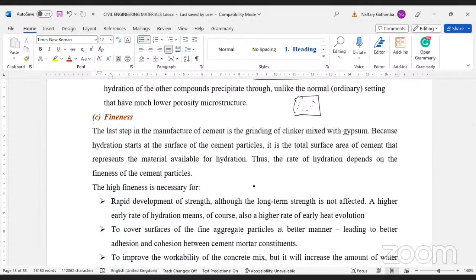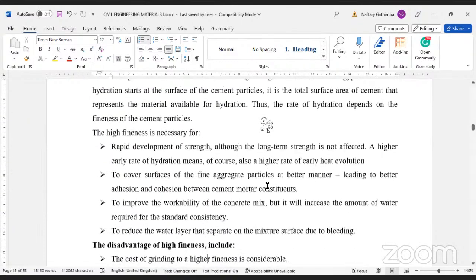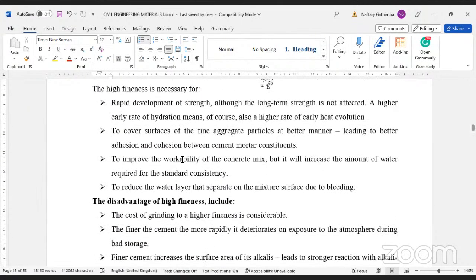So the last step in the manufacture of cement, we saw, is grinding of the clinker with gypsum. So what is the importance of grinding? Cement needs to be fine, because the finer it is, the more surface area is exposed for these particles to come into contact with water. And when they come into contact with water, hydration occurs. The rate of hydration, we have understood, is the chemical reaction that occurs when cement comes into contact with water, and that's how strength is gained in cement. So the rate of strength gain in cement, or the rate of hydration, depends on the fineness of cement. So we may need to have a cement with very high fineness if we want cement that reacts quickly to develop rapid strength.